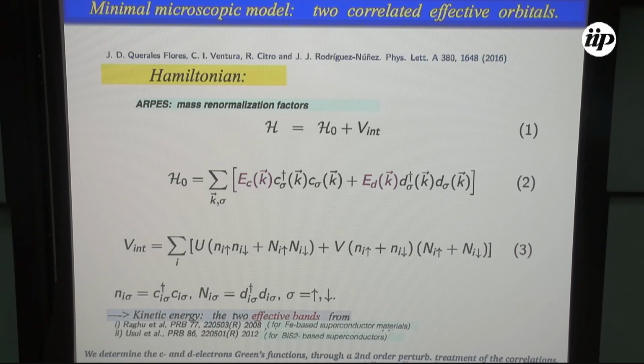Here I mentioned the bands. Actually, we had applied this also for the pnictide compounds, and I told a bit about those results when I was here in Natal 2 years ago. So basically what we did in that case, we used other bands by Raghu, Scalapino, etc., for the iron pnictides to look at the spectral properties. And this time we used it for this lanthanum oxygen fluoride bismuth sulfide BiS2 superconductor.